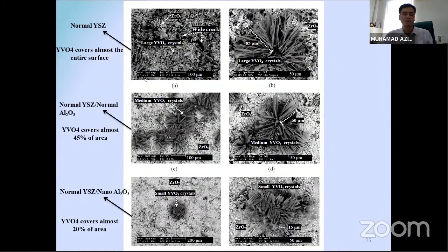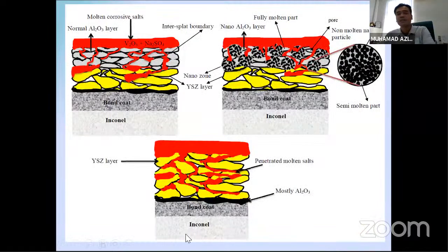So meaning it's good to have the nano alumina as the third layer. Based on our research, we found that the nano alumina as the third layer can prevent or reduce the formation of the corrosive salt. This is basically the mechanism behind it. If you have only YSZ, the corrosive salt, as I mentioned just now, the vanadium pentoxide or sodium sulfate, at high temperature can diffuse and go to the bond coat, and it will become destructive to the bond coat area here.